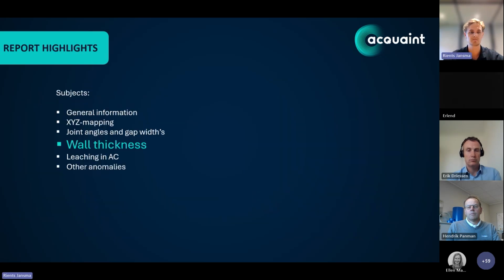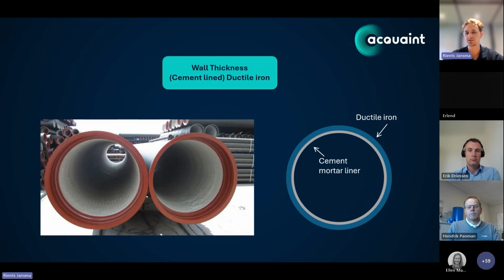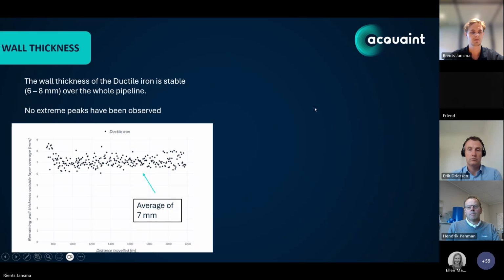The wall thickness. Starting with the wall thickness of the cement-lined ductile iron. On the left, you see a picture of a cement-lined ductile iron pipeline, and on the right, a schematic picture. So the wall thickness of the ductile iron is stable at around 6 to 8 millimeters. On the left side, you can see the graph. You can see the remaining wall thickness, and at the bottom, it's the distance traveled. The average is around 7 millimeters, so it goes from here 6 till above 8. Some parts are a little bit above 8 millimeters.